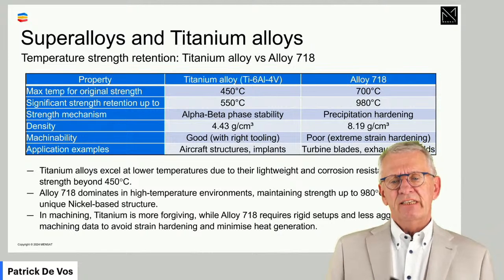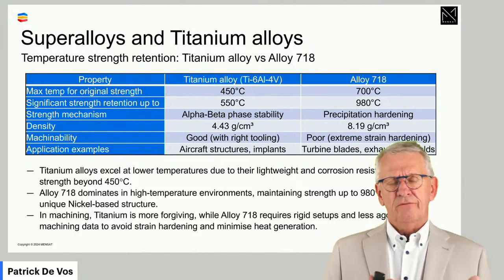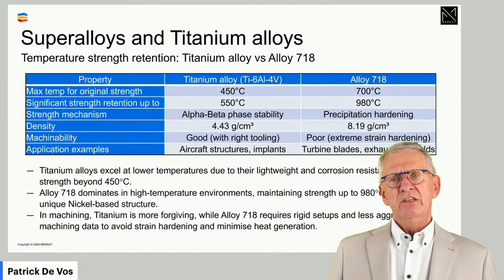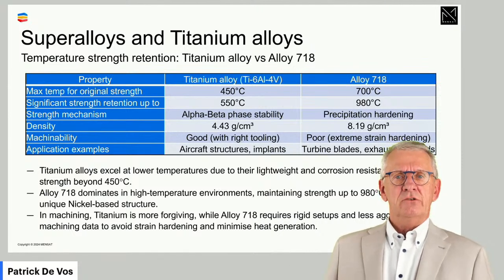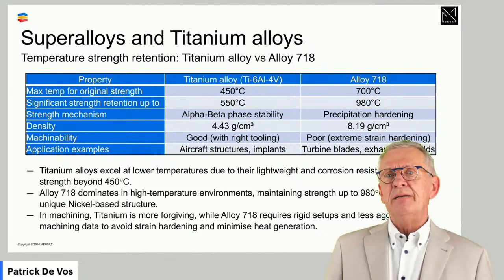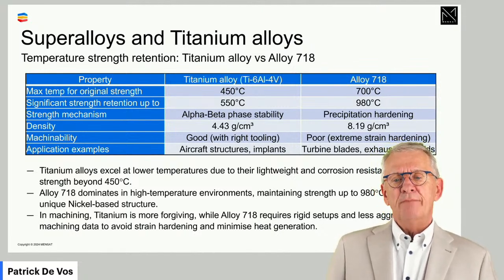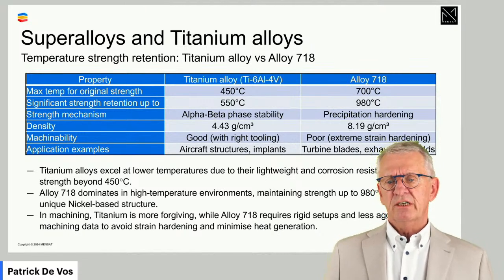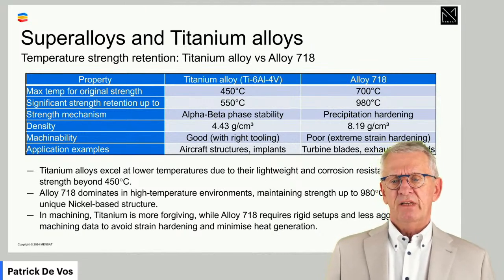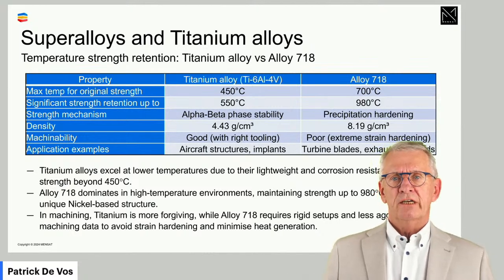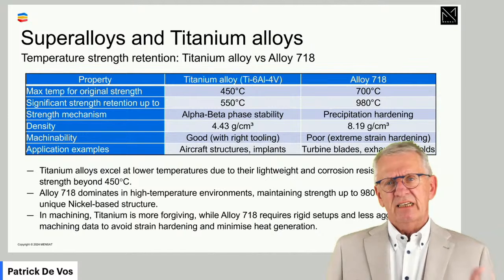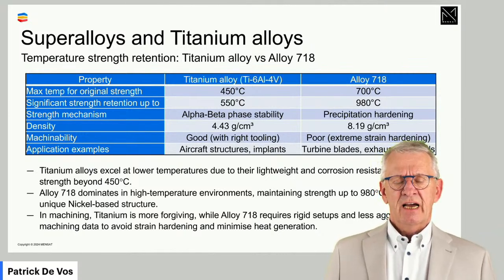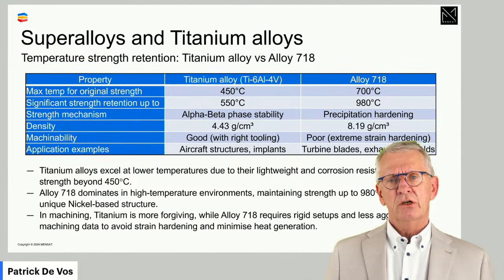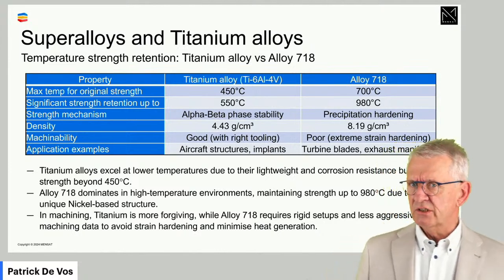However, when temperatures go above 400-500 degrees Celsius, titanium starts to lose its strength, while Inconel 718, alloy 718, keeps the strength. And keeps that strength up to close to 1000 degrees Celsius, where titanium by then already lost nearly all of its strength. That's a big difference. The other big difference between the two materials is the density. What you see is that titanium has a low density, whereas superalloy has a high density, even perhaps higher than traditional steel.